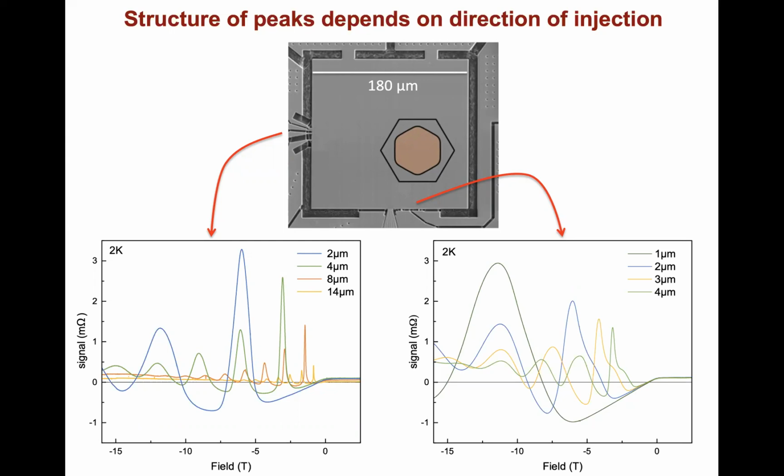For a long time, we were trying to think of ingenious ways that that structure could itself somehow be a viscous effect. But then Maya began to really worry that maybe the ballistics that we were seeing were very much more strongly influenced by the faceting of our Fermi surface than we thought they were. So again, beautifully, she just did a really direct experimental test of this. She fabricated another focusing device where everything was identical along that edge and along that edge, except that because she changed the edges by 90 degrees, she had a different effective Fermi surface orientation for the distribution of how the injected electrons were going to be.